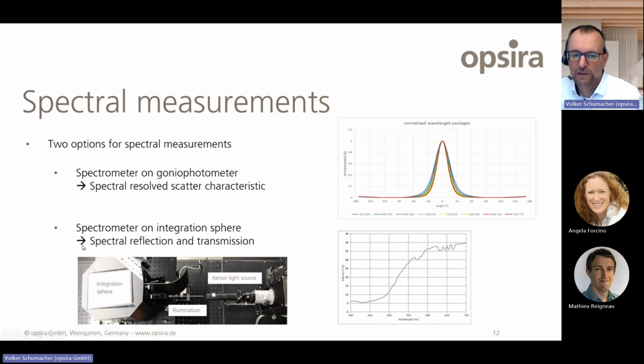And also we do measurements with the spectrometer with an integration sphere, where we can measure at one angle of incidence the transmission spectra and the reflection spectra. And based on that data, we can also calculate, for example for transparent materials, the absorption coefficients of materials.